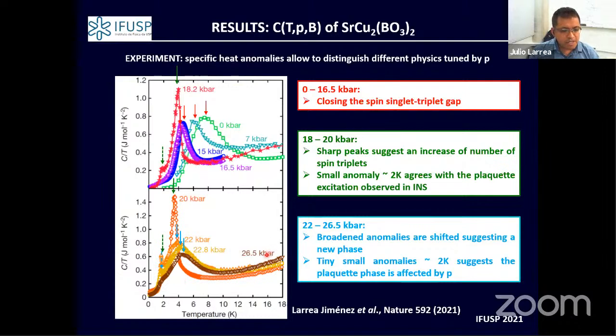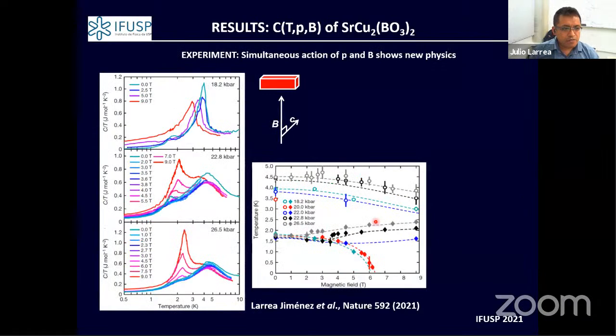So the observation suggests we have at least two different phases, and something significant happens between 18 and 20 kilobar, which tells us there could be a quantum phase transition. In order to infer more about the physics of this problem, we also apply magnetic field combined with the effect of pressure.